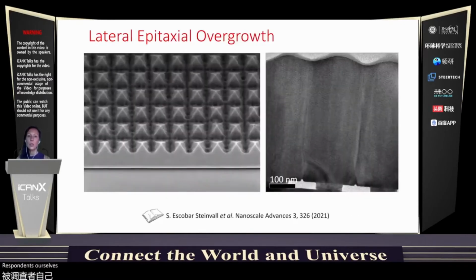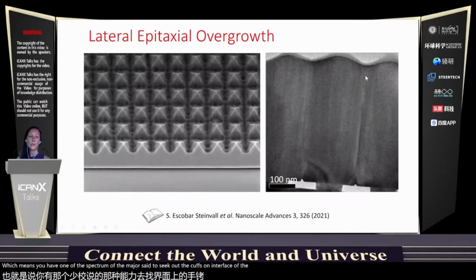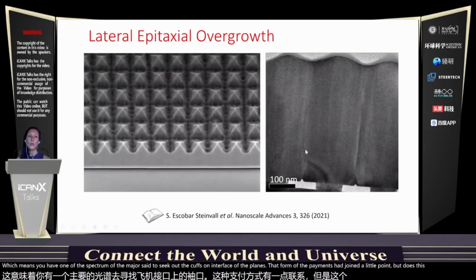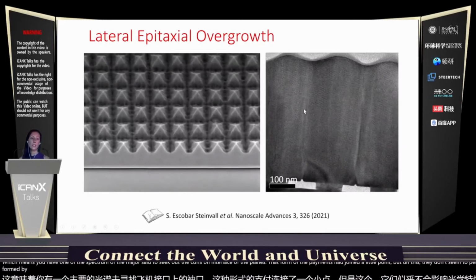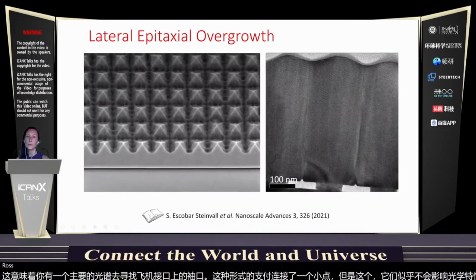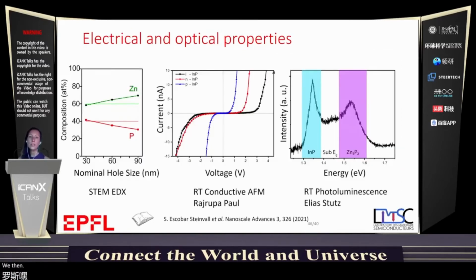Here you have one of these textured layers, and you see the interface of the grains that form from the pyramids that join at some point, but they don't seem to perturb the optical properties. And so this is the thin film that we have formed by this textured growth. We then look at the optical and electrical properties.